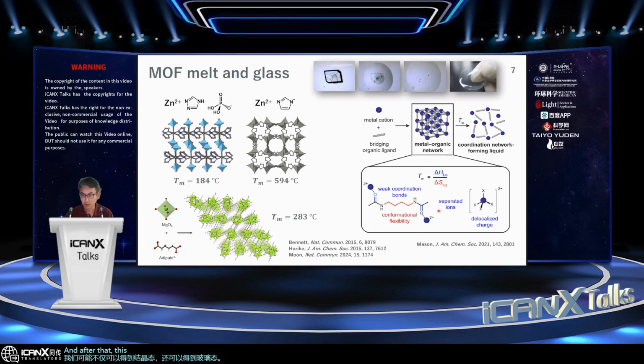And this is a scheme by the group at Harvard. As I introduced, the melting temperature is delta H over delta S, which lies between the crystalline solid state and the melt state. By combining metal ions and ligands, we can, for example, reduce the melting temperature by increasing delta S through increased flexibility in the ligand, and decrease delta H by tailoring the strength of the chemical bonding, to realize the melting temperature before decomposition.